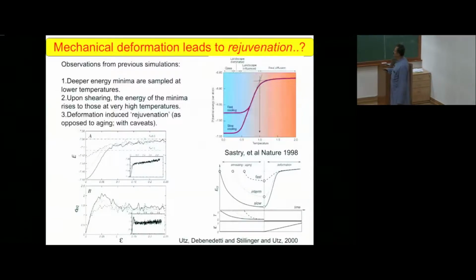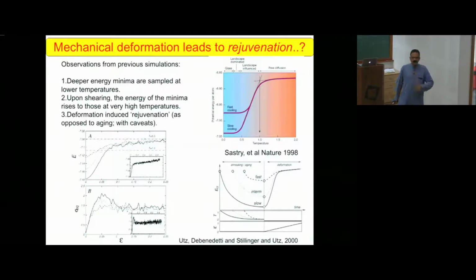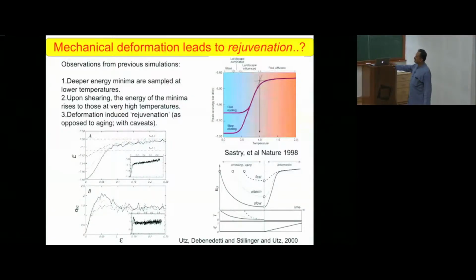And then if you take, this is what is depicted here, so I anneal the system up to some time, you end up with some local energy minimum down here, and then if I now apply shear deformation, I'm pushing the energy up, okay? And what is found in this many years ago work is that you seem to increase the energies up to this threshold energy that you found, okay? So the flowing glass will have this high energy, yeah?